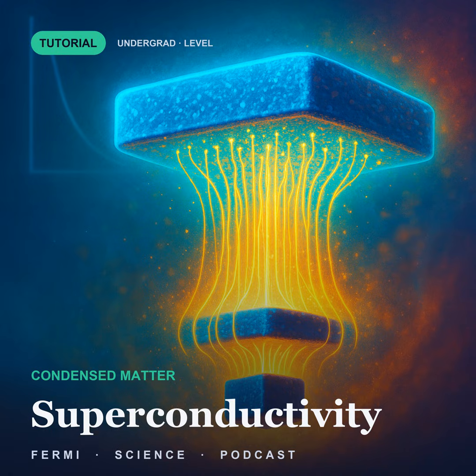And because the answer is an exponential of -1 over the coupling, no expansion in powers of the coupling could have found it. And the question you have that I have not answered: why the mean field treatment is allowed. Every step of the gap equation replaced the other pairs by their average, and Landau's expansion did the same at the level of the free energy, and that move was visibly wrong for liquid helium near its transition. Here it is not merely tolerable, it is nearly exact, and I think the reason is the length.